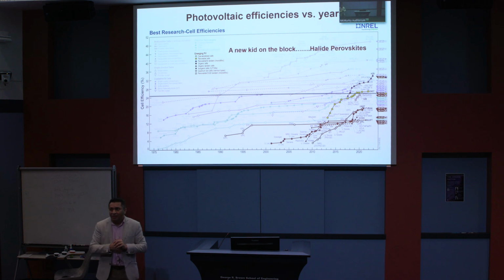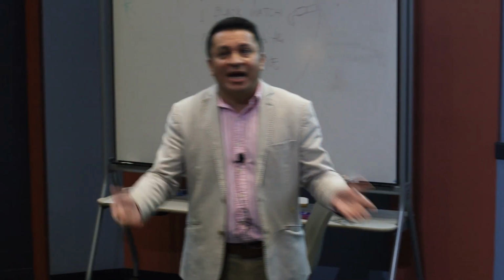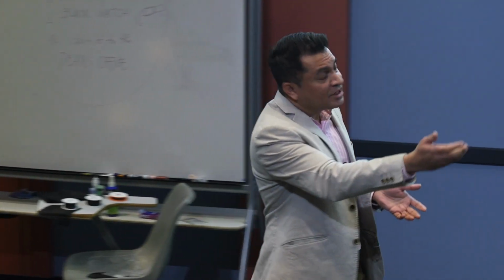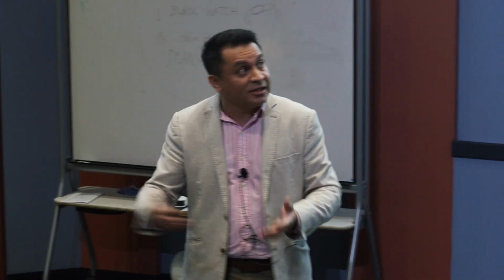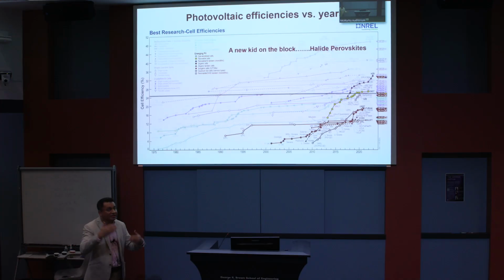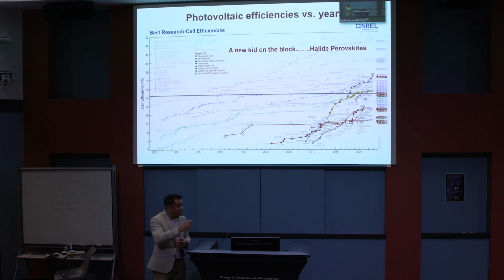And so what happened about a decade back is that there is a new kid on the block, known as these solution process halide perovskites. It's a new class of materials which has surpassed the efficiency of silicon. In fact, if you combine this material with some other materials, for example with silicon or itself, you can get to very, very high efficiencies, which is shown on the top right here. We are already at 32%.